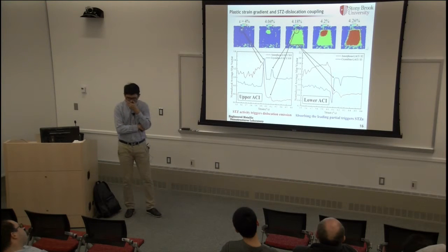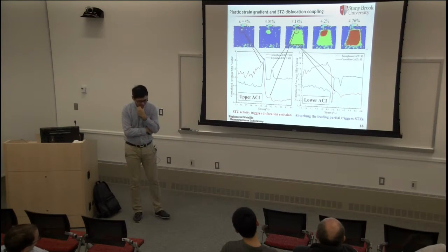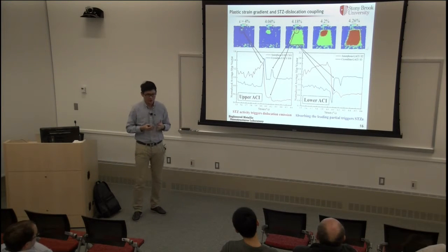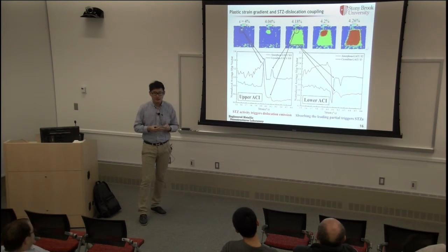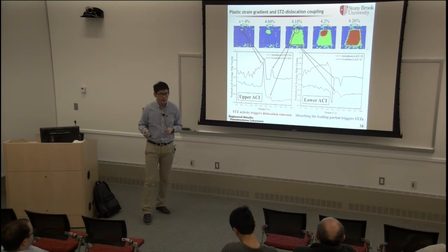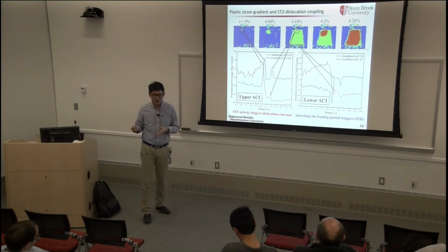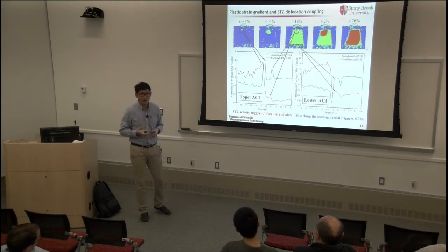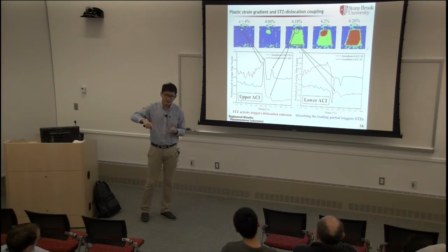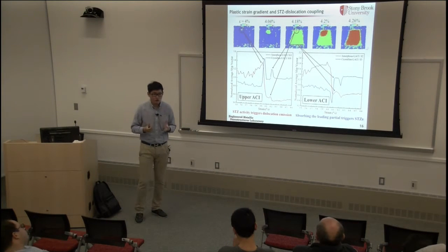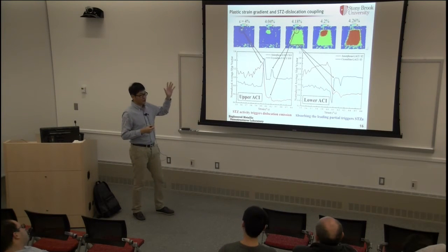Thank you for your question. Let's talk about nanocrystalline first. In nanocrystalline material, the dislocation is emitted from the grain boundary. There are a couple of theories. One theory talks about the stress concentration, which triggers the dislocation, and another theory is about the free volume at the grain boundary and the triple junction, which can migrate to the point and trigger the dislocation. So this could both happen in our nanolaminate structure.